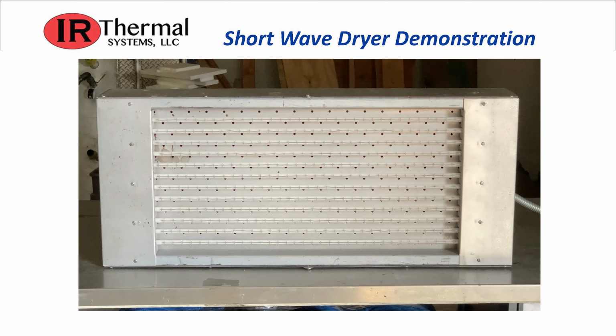And the lamp itself is made of tungsten inside with a gas that's in a sealed quartz tube. These elements can get up to 3,500 degrees versus 1,800 degrees on the medium wave. So now we'll go ahead and turn it up, and we'll bring it up slowly because it does have a high inrush. So if you're using an SCR like we are, you want to make sure you have a little bit of a delay so that you don't blow fuses. We use high-speed fuses on the SCRs to protect them.